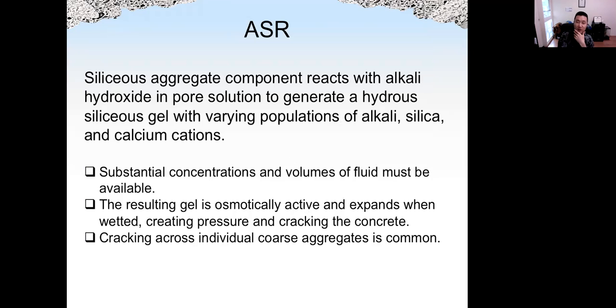Okay. So here is more information about ASR. Let's just read it together. Siliceous aggregate components react with alkali hydroxide from the pore solution to generate a hydrous siliceous gel, with different alkali, silica, and calcium cations. High concentration and volume of fluid must be available. So we need water, we need moisture for ASR to happen. The gel is osmotically active and expands when we have moisture. So that will create pressure and potential cracking in concrete.